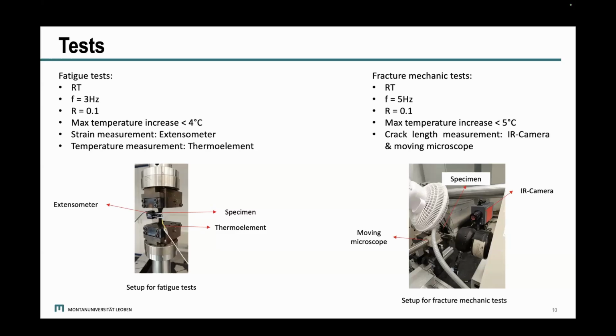And also for all of the tests, the temperature increase in the specimen during the test did not exceed 4 degrees Celsius. For the fracture mechanic tests, you can see our setup. Also, we performed the test at room temperature under 5 Hertz and a stress ratio of 0.1. And we measured the crack length in the specimen with two different methods, once with a moving microscope, also manually, and once with an infrared camera.